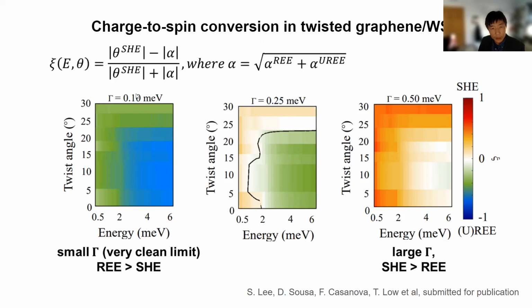So what I have here is we go from low disorder limit to high disorder limit, and what we have here is a plot of the ratio between the spin Hall effect and the Rashba Edelstein effect. When you see a red color, it means that the spin Hall effect is dominant. If you see a blue color, it means that the Rashba Edelstein effect is dominant. So what this is telling us is that when the disorder is very small, the Rashba Edelstein is dominant, but when the disorder is large, the spin Hall effect is dominant.